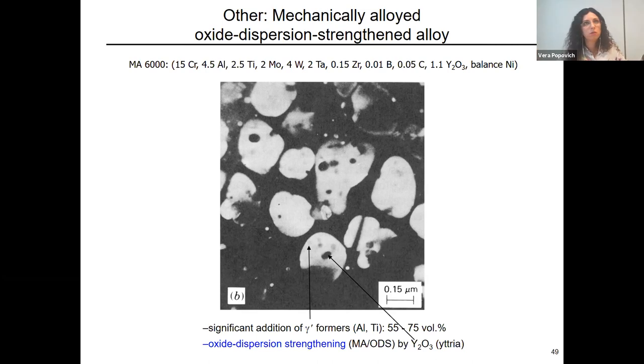They are put in high capacity energy mills, and they blend it together at a really high energy. This leads to a really homogeneous and fine-grained structure of the particles. But more importantly, with this kind of technology, you can blend in much more of this gamma prime. So you see this gamma prime, these dark areas, up to 55 to 75% of gamma primes, which you can add into your material with these technologies, which is not possible with more conventional techniques.